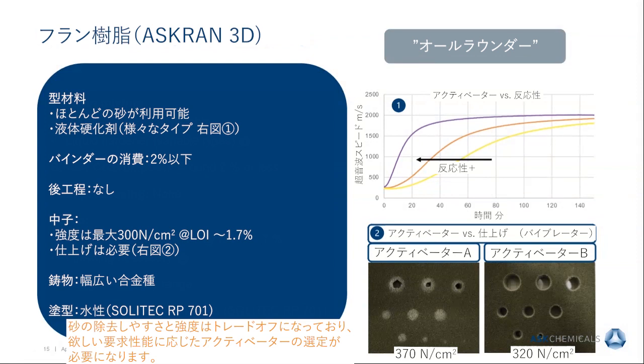And one can see that using either activator A or B, a very different appearance of sand adhesions can be obtained, but it also comes at the price, in this case, of reduced strength. So there has to be a balance, which, by choosing the right activator, can also be suitably selected.